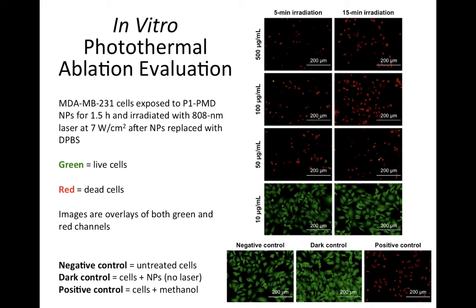This is the result of the spectral differences of these two nanoparticle types: specifically, the absorption peak of P1-PMD nanoparticles more closely aligns with the wavelength of the laser used in these studies, thereby producing a stronger photothermal effect at equal concentrations. In conclusion, we have reported the preparation of two types of near-infrared absorbing conductive polymer nanoparticles and established their potential as agents for laser-induced photothermal therapy.